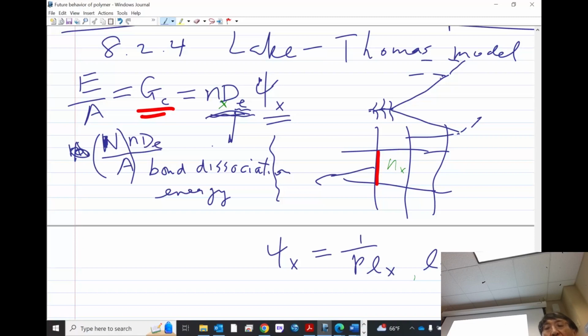All I am trying to do is to show you that this is proportional to the square root of the strand length, or the number of bonds in that strand. So this is the final important result, that you can toughen the material. In other words, your polymer will be tougher. Remember, GC is defined as toughness, so a tougher material simply means a larger GC. And this GC is expressed this way, so people would say that your material is tougher if you have a long chain between crosslinks, in some sense.